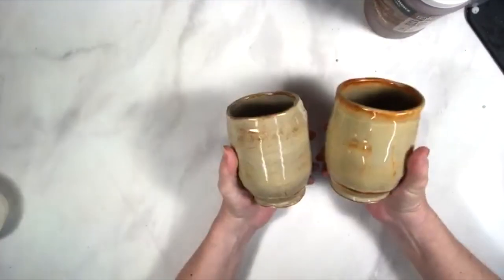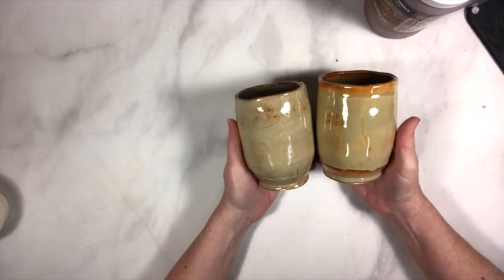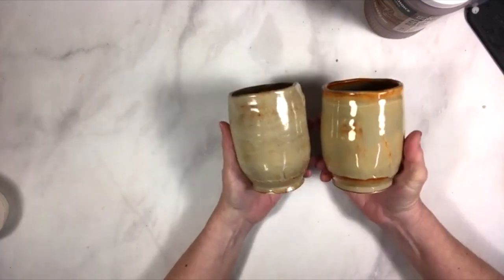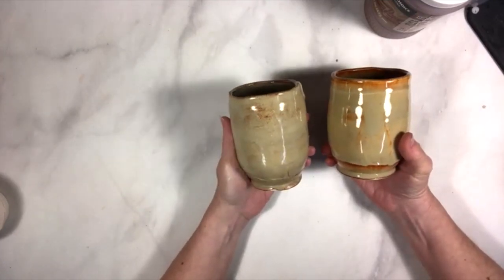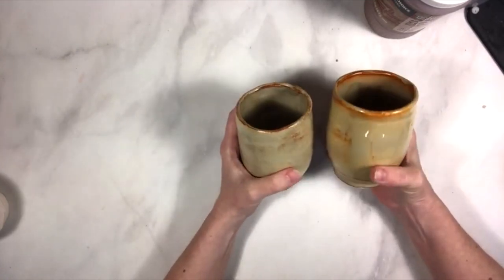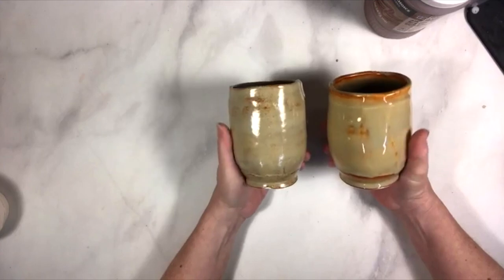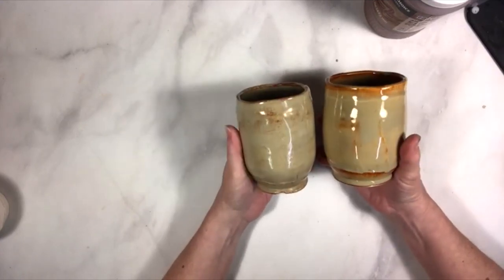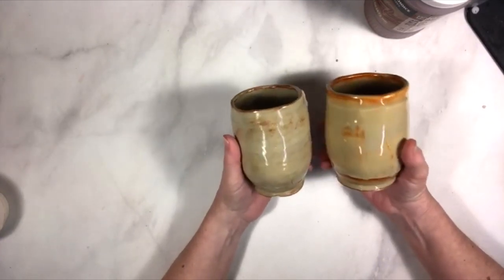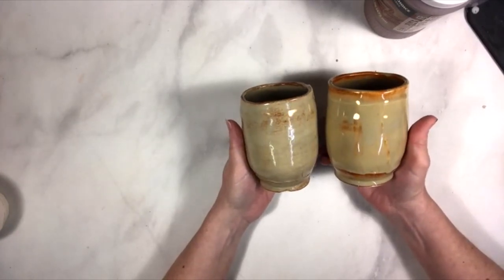In a side-by-side comparison the colors are similar but not quite the same. Albany Slip Brown is a little warmer toned and definitely glossier. The Chai Gloss is a little more satiny and has slightly less variation between brown and creamy color, but they're both very nice light color glazes when applied thick enough. If you're getting a dark red-brown with either one, the problem may just be that it's not a thick enough application — both are very sensitive to application thickness.